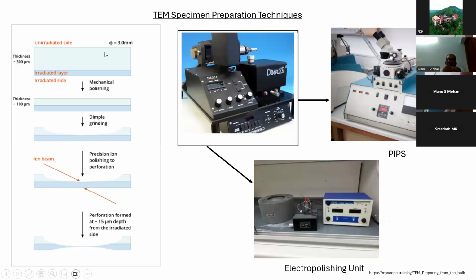Whatever be the initial thickness, initially when I was doing TEM, I used to section it close to 600 or 800 microns, because if you try to section it below that, around 400 or 300 microns, it is possible only by the use of very good low speed saw blades. Basically you can get it, but the chance for the specimen to be bent is very high.